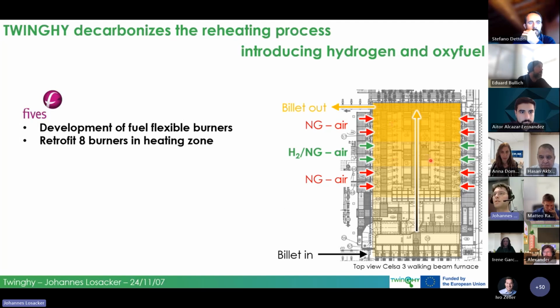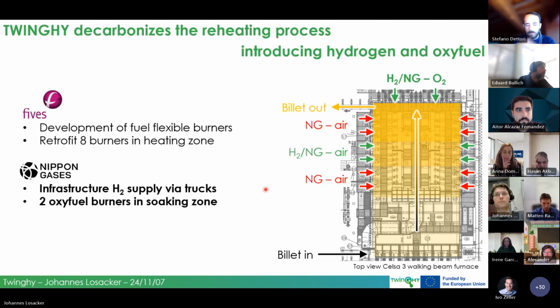So in the heating zone, which is one of 3 furnace zones consisting of 8 burners, these are getting retrofitted in the furnace, and this heating zone is actually the one with the greatest share of energy contribution. So it's quite reasonable what we are retrofitting here, that is able to be operated on hydrogen later on.